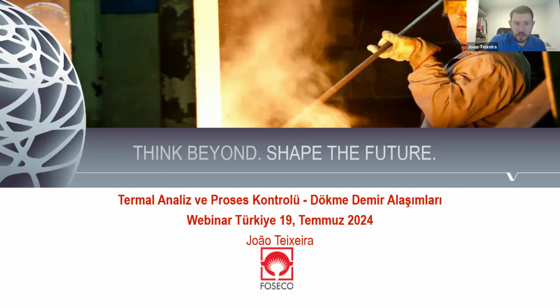But normally, to improve the production of gray cast iron, so to improve the graphitizing factor, we need to promote the formation of type A graphite. And one of the best inoculants to promote this is the strontium ones. So strontium is really good to promote type A graphite. So by using strontium, we can improve the graphitization.